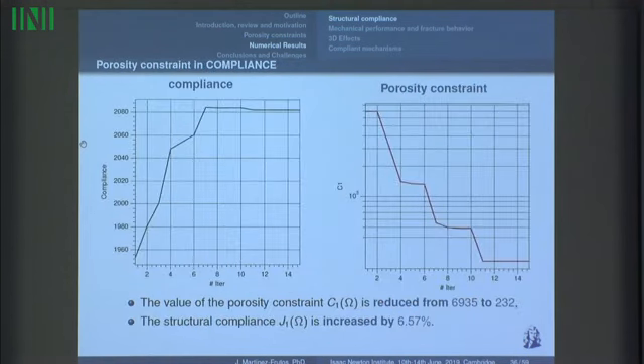So this is the evolution of the compliance and the porosity constraint for the first case, and we see here that we just have 15 iterations accumulated after all the iterations that we needed to obtain this design. Once we obtain this design, after 15 iterations, we have a reduction in the porosity constraint from this number to this number. So we have a great reduction in the porosity constraint that is achieved at the cost of degrading the compliance. The compliance is increased by 6.5%, right?